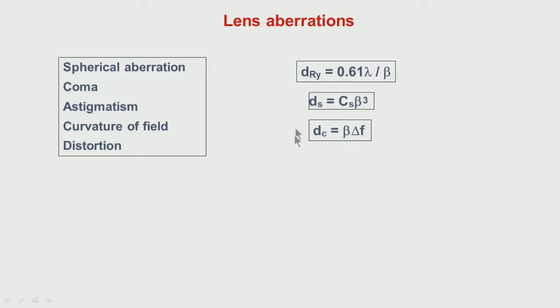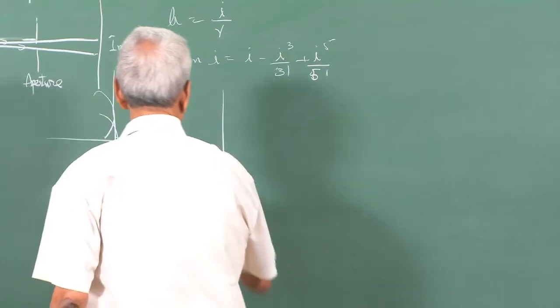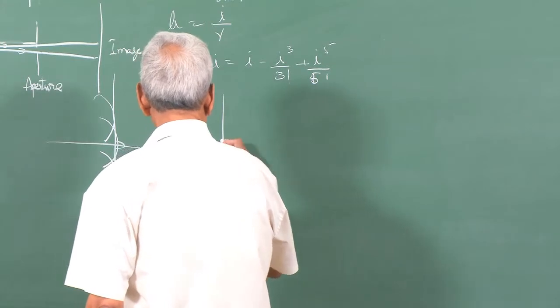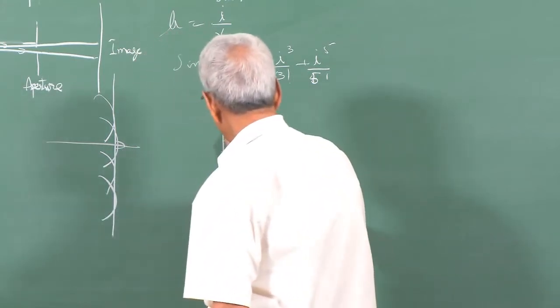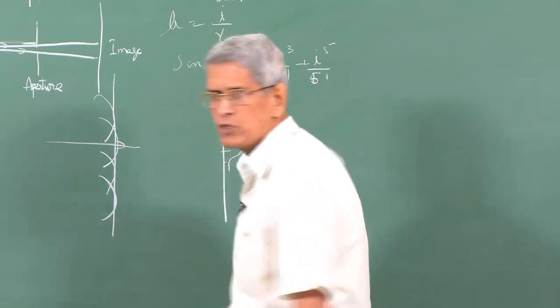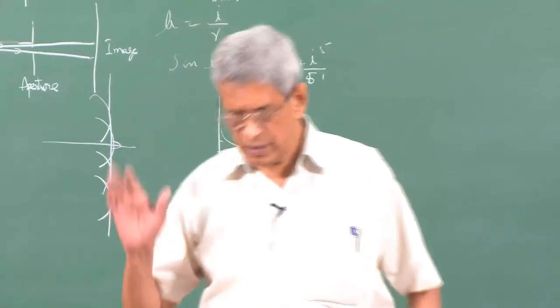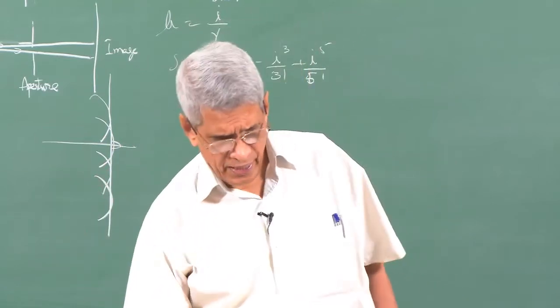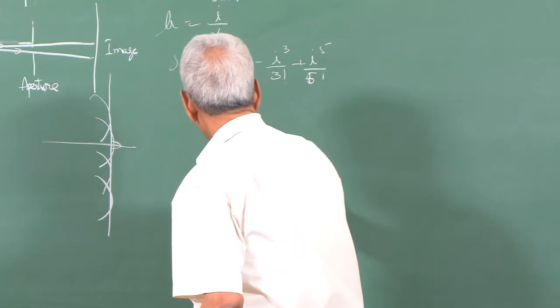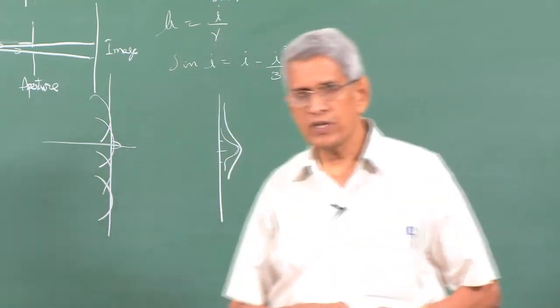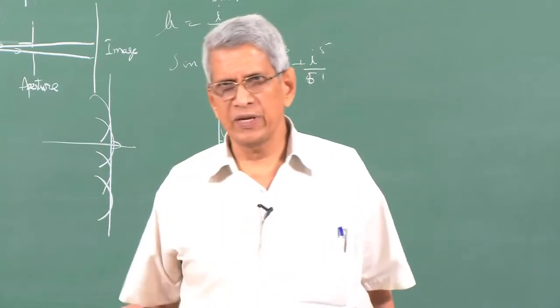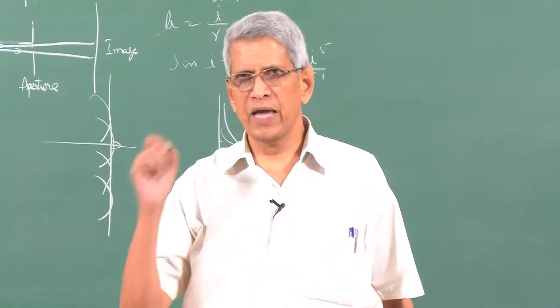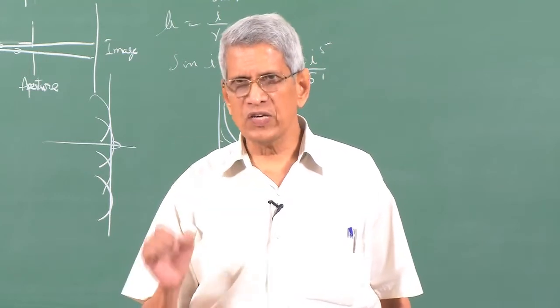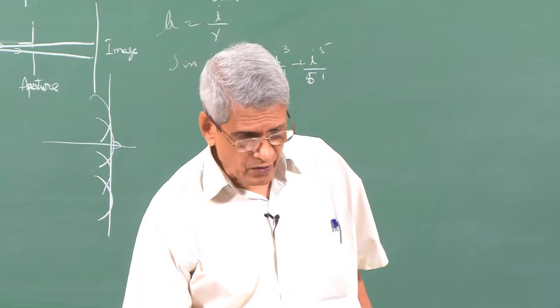And if we consider all these effects, the image distribution in the image plane is essentially a variation from the center. This variation is considered to be something like a Gaussian distribution. If you take a Gaussian distribution, there are many of these adjacent peaks, one Gaussian peak and then another Gaussian peak which comes like this. The total effect, with respect to standard deviation, is obtained by adding the squares of the standard deviations together and taking the square root. That will give the standard deviation of the overall effect. That is what is essentially being done here.